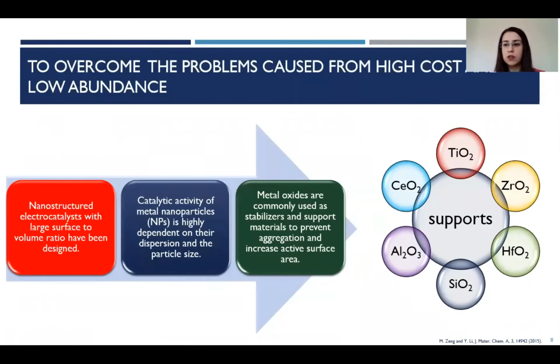To overcome these problems, nanostructured electrocatalysts with large surface-to-volume ratio have been designed. Catalytic activity of metal nanoparticles is highly dependent on their dispersion and the particle size. So metal oxides are commonly used as supporting materials to prevent aggregation, increase dispersion, and decrease the particle size. Also, metal oxides are used to increase the active surface area of the metals. Ceria, titania, zirconia, hafnia, silica, and alumina are the most commonly used metal oxides in the literature.